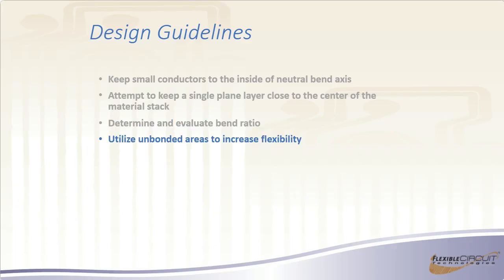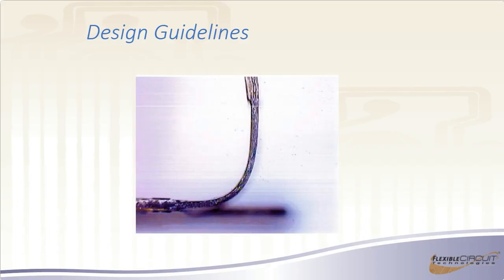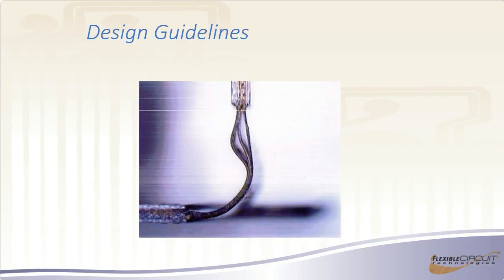Another way to increase flexibility is to utilize unbonded areas, and by that I mean this is a 7-layer rigid flex cross section. And there's 7 layers in the rigid area and 5 layers in the flex area. And the customer was having a problem with this because it was just too stiff and they weren't able to get it in. And so we recommended going with an unbonded construction. And what we do is we unbond only the flex areas. So the individual layers can be unbonded. That can be any combination. And what we did is we did a 2-layer, a 1-layer, and a 2-layer. And that made it a lot more flexible. And the customer really liked it.